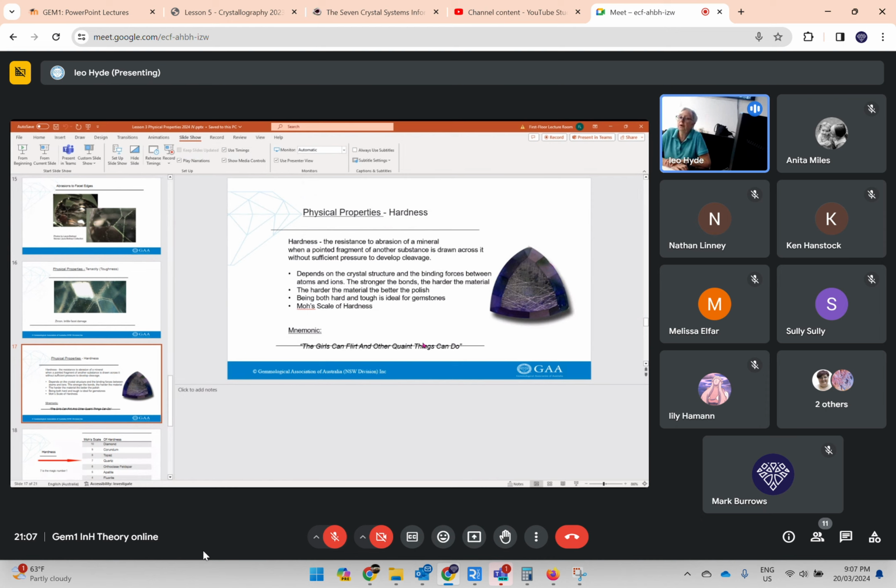So one of the things, if we're looking for diamond or moissanite, which is one of the Johnny-come-latelys as a diamond imitation, moissanite's doubly refractive, and diamond comes from the cubic system, so is singly refractive. So that can be one of the clues between diamond and moissanite. Having said that, the way they cut the moissanite disguises that, but you've got to look for it.